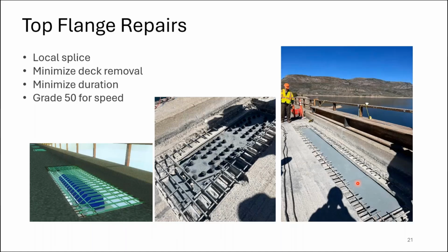So some of them did end up being larger in the top flange, where we did have a lot of fillet weld cracking. So you can see a larger section. This is one of our local repairs. And as I said, those were 50 KSI and were designed to try to minimize our deck removal and the duration of the impact to traffic.